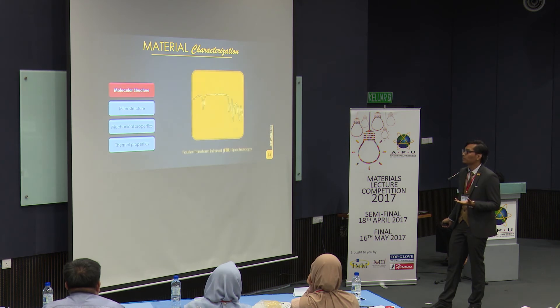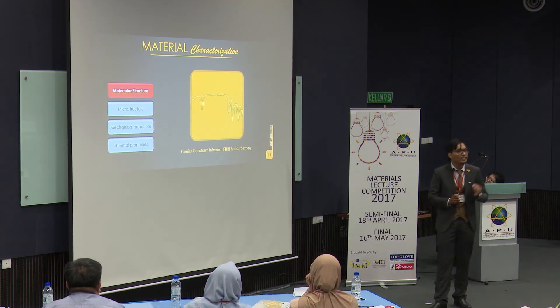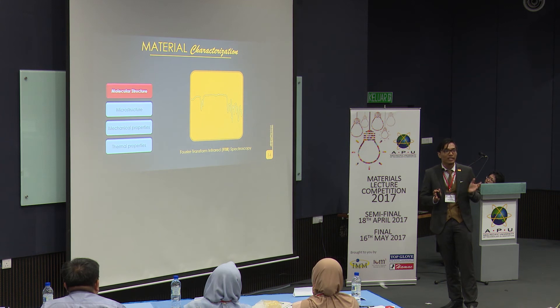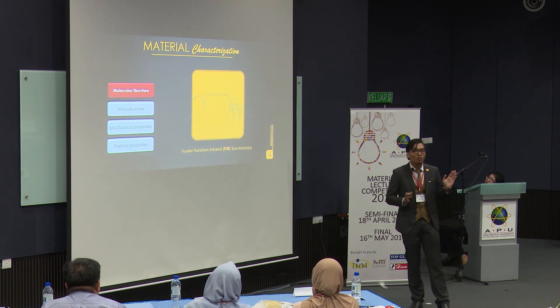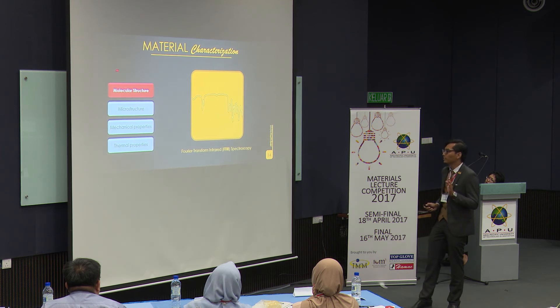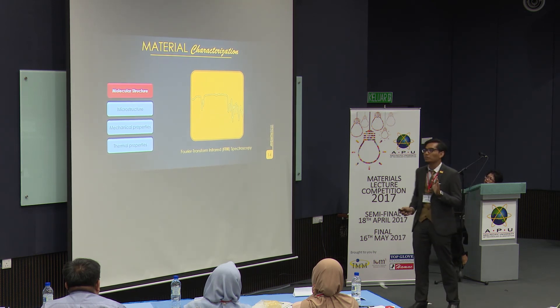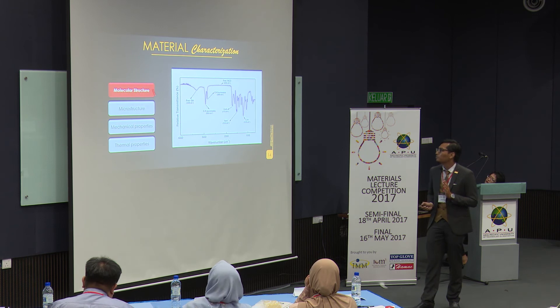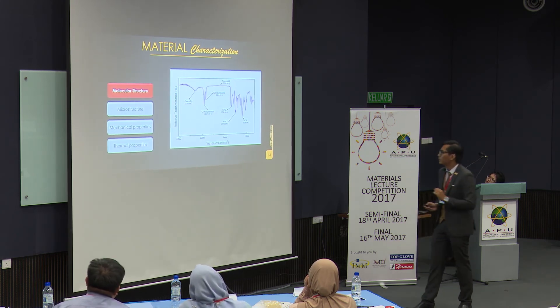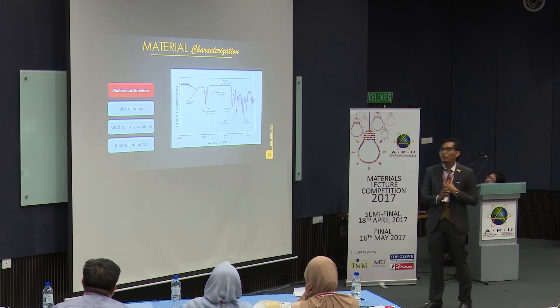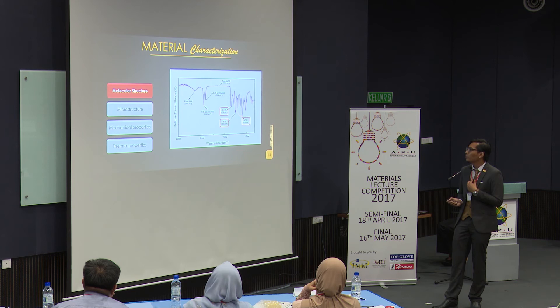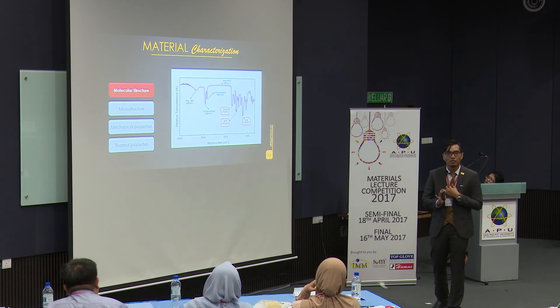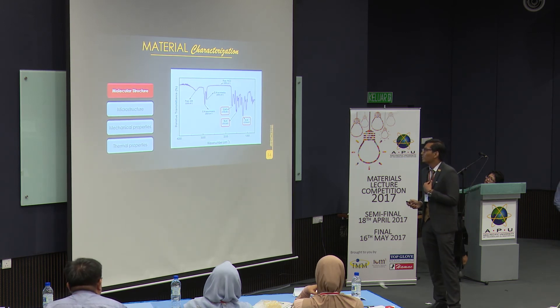Now that you have produced your foam, you need to test it — is it strong enough, is it suitable for certain applications? Among the many characterization processes, one is testing for the molecular structure using Fourier Transform Infrared Spectroscopy, called FTIR. Here is the basic FTIR spectrum for polyurethane. The three peaks to highlight are C=O, N-H, and C-N — these are the characteristic peaks for polyurethane, confirming that polyurethane foam has been successfully produced.